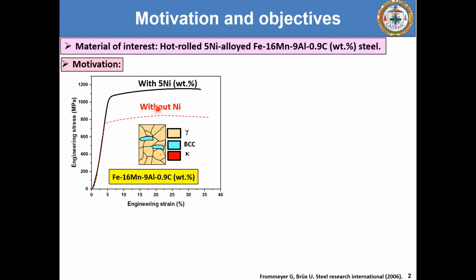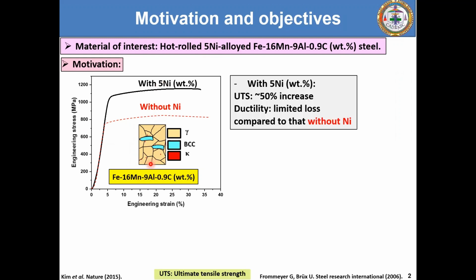So now when we further add 5% nickel to this particular steel composition, what we can clearly observe is that we have the ultimate tensile strength increased by nearly around 50% with a limited loss in terms of ductility when compared to that without nickel, of course. So this means that when we add nickel, we have a strength increase. Now the question is, why is the strength increasing?